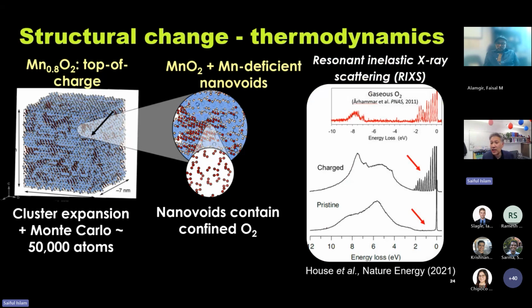With my colleagues at Oxford, Peter Bruce and Rob House, they've done some oxygen K-edge resonant inelastic X-ray scattering, RIXS. What I'm showing you is some data here for the pristine at the bottom, then the charged system. And you can see there's some signature which is not seen in the pristine. And that signature relates directly to gaseous O2, molecular O2. And then on discharge, we lose that signature and we form O2 minus again. And I stress on discharge, we're putting lithium back in, and that is stabilizing O2 minus species, but in different environments, and hence the hysteresis.